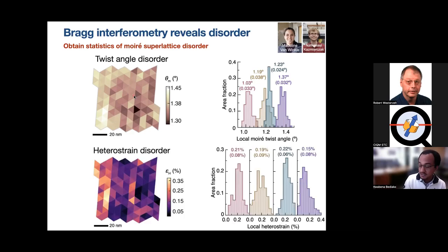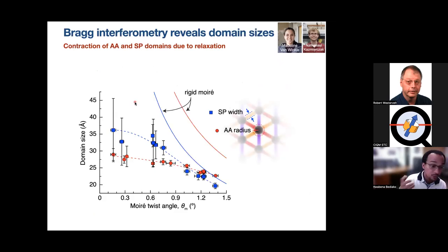And so we can obtain some statistics, for instance, on apparent twist angle disorder and disorder in heterostrain over these samples, and use that then to interpret what we see, as I'll show later. We can also look at the size of these domains because we can measure the saddle points, the AA regions, the AB regions. We can measure the size of those domains, and what we see is that the AA and saddle point domain sizes are being attenuated by this relaxation process, whatever it is, as we'll talk about in a bit, from what you expect from a rigid moiré.